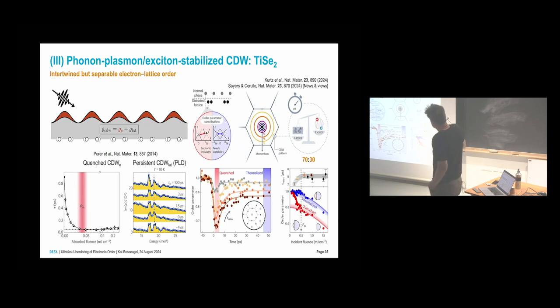And then there's this very recent publication from Claus Ropers' group in Göttingen, where they have measured this using ultrafast LEED, and where they have weighed the contributions, lattice versus excitonic, by looking at the superlattice diffraction peak, at the response of this peak. They see that the intensity of this superlattice Bragg peak is quenched very fast, by about 30%, and then it is persistent. This corresponds to the periodic lattice distortion, which is persistent, while 30% of this ordered state is quenched. So fast electronic quenching, persistent lattice distortion.